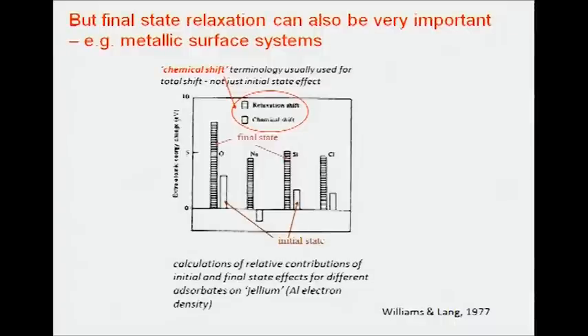And this is just a model calculation from Williams and Lang at IBM back in 1977. It's a calculation for these atoms, oxygen, sodium, silicon, and chlorine, on a jellium surface. So it's a rather idealized calculation, jellium with an electron density corresponding to aluminium. And it shows the components of this core level shift that arise from the initial state, and that's labeled here rather confusingly chemical shift, but it's just the initial state effect. It's the change in the one electron binding energy. And this is the final state, in other words, the relaxation. You can see, as you might expect, that the chemical shift, for instance, is opposite for electronegative oxygen and for electropositive sodium, but you've got this large effect in the final state, and that varies for these different atoms.